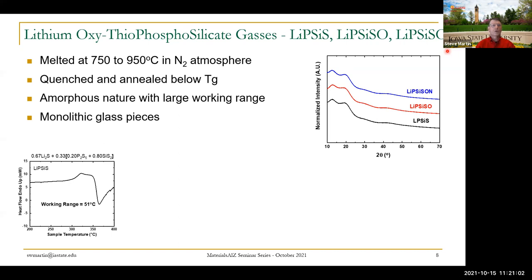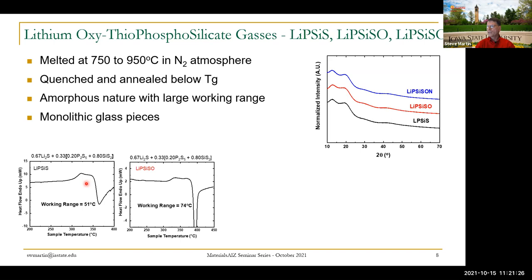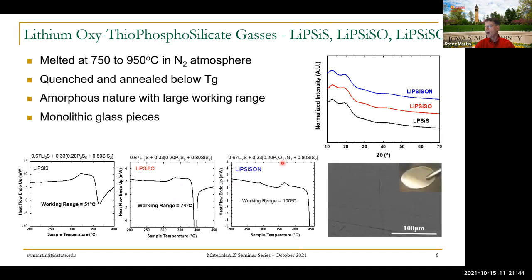One of the first tests we do is thermal stability. And here I mean thermal stability against crystallization. You can see they've got a glass transition temperature around 300 degrees Celsius. This is a mixed glass former, phosphorus and silicon. We vary these ratios a lot, and I'm just using one here, but you can see the working range is rather modest, about 50 degrees above the glass transition temperature before it crystallizes. We can add some oxygen to that glass. I'm sorry, there's a typo here. This should be P2O5. I didn't quite get that one fixed. We call that oxysulfide glass, and you can see we increase the range to about 74 degrees. And then when we add the oxygen and the nitrogen, then we increase that working range out to about 100 degrees. And I don't know if you can see this or not.